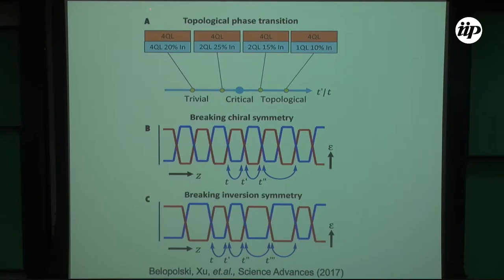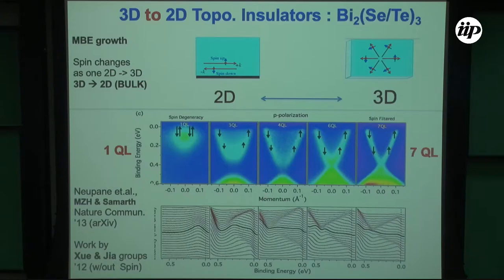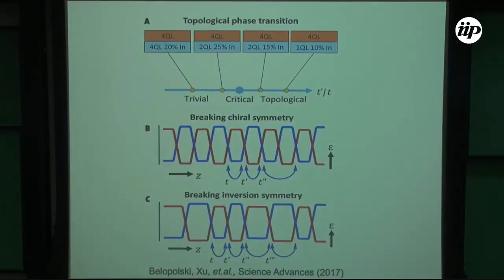Without the topological transition, I should see a gap Dirac fermion here. But if it is becoming topological, it doesn't matter which surface I terminate, it will then show a Dirac cone. So in other words, I expect to see a Dirac cone inside this thing, this 4QL thing. There will be a small Dirac cone if it is topological. That would be my experimental diagnostic. That way I figure out whether these multi-layers we fabricated have crossed the critical point. So this is my experimental diagnostic.